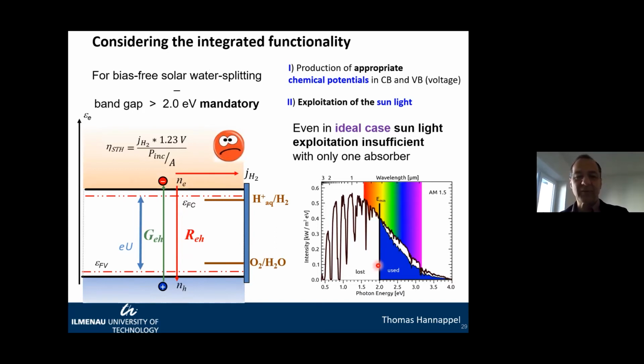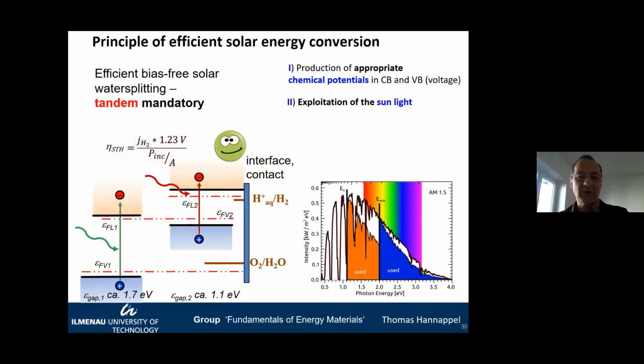We cannot improve it by just using one absorber. So the answer is we need to use tandem structures. In a tandem structure, we can do both. We can produce enough free energy to split water, as you can see here. And secondly, we can exploit the solar spectrum much better. This you can see here. This is a very important point. And this leads us to the theoretical highest efficiencies which we could reach to split water.